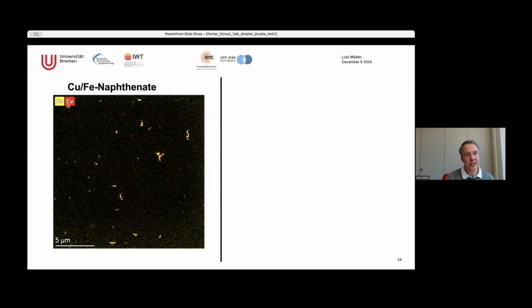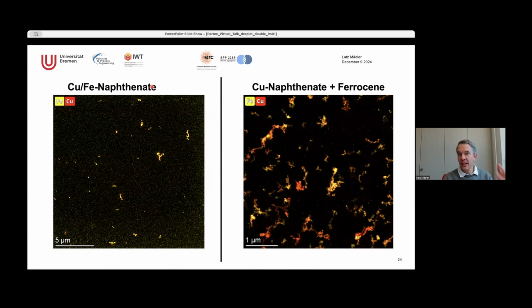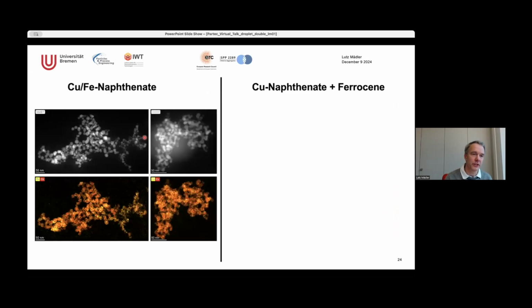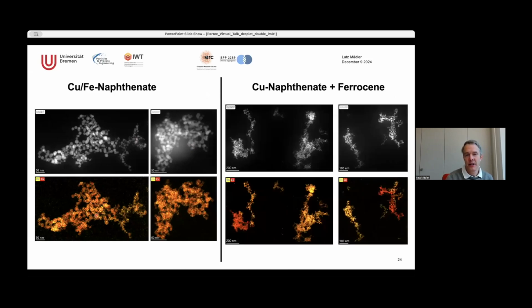And here you see iron and copper is always together in the case where both of them come out at the same time with the explosion. While naphthenates of copper and iron evaporate differently in the single droplet, you get more iron containing particles, these are the iron containing particles, and more copper containing particles. So basically they look more separate. And this gives us a very clear design principle. I think I have some better pictures even here, some more magnification. So these are really mixed within one particle, while these are not really mixed in one particle.